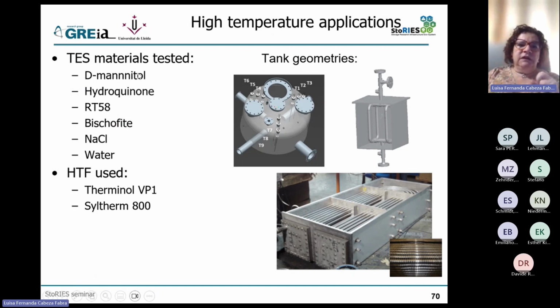An example was the test we were doing with the mannitol. When we were working with the mannitol in the lab, we found that we had 2 peaks in this material. And this is due to the crystallization, with the phase arrangement of this material. And then my PhD student was doing the test in a tank like this one in the image, the one at the bottom, which had 100 kilograms of the mannitol. And he found also 2 peaks, but one was at a different temperature than we were looking at in the lab. Of course, the first thing when you see this, as an advisor, you tell him, something is wrong, repeat the experiment. But we kept having the same behavior.